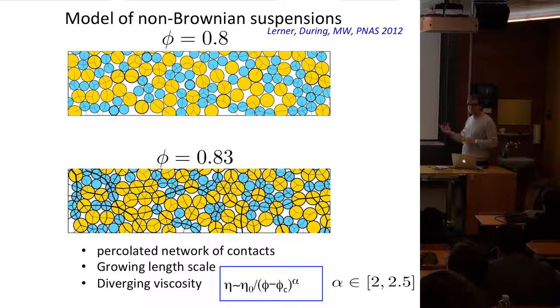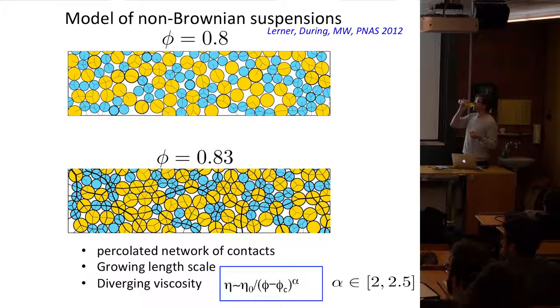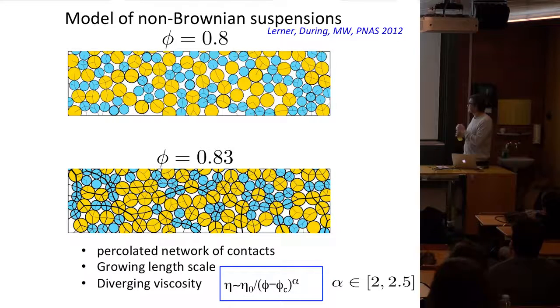In a real suspension, as a function of strain rate, at small enough strain rate, you would be like that, and then at some point you would have a transition to an inertial regime, where it would look more like a granular flow in air. And you don't have hydrodynamic interactions; you just have... Yes, so that's a very simple model. Yeah. For those who know, it's similar to the Olsson and Teitel model.